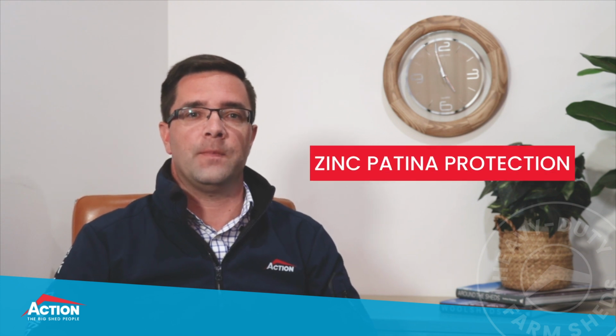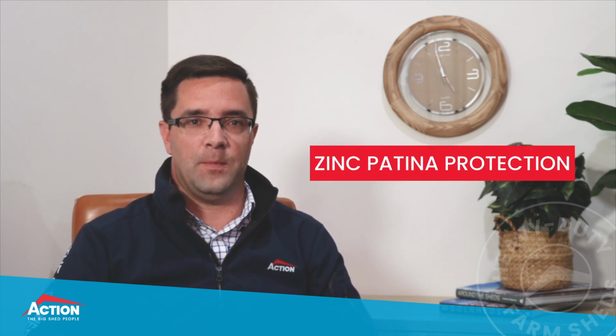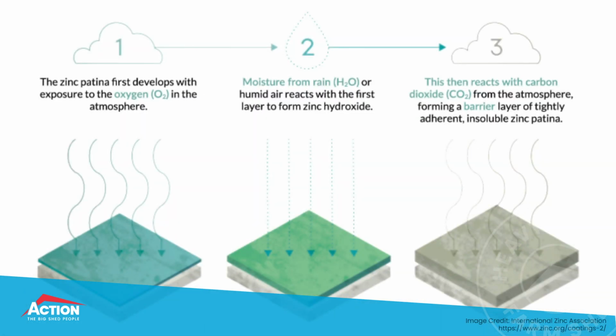The third type of protection is called the zinc patina. This occurs when the zinc metal is exposed to the oxygen in the air and reacts with the oxygen to form a zinc hydroxide. Over time, the zinc hydroxide is exposed to carbon dioxide in the air, a thin layer of zinc carbonate forms. It's this passive patina film that is tightly bound to the zinc of the galvanized coating and is what makes a hot dip galvanized coating so durable.